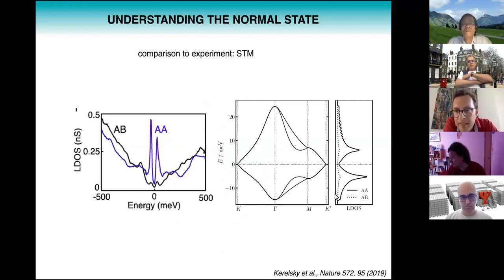So here's again the band structure of twisted bilayer graphene. And from the band structure, we can, of course, calculate the local density of states. And this is done here. And so you see that the local density of states indeed has two peaks. And these peaks actually derive from states near the endpoint of the unit cell. So this is, of course, a point where you have a saddle point in the band structure. So what you see here is a well-known Van Hove singularity.